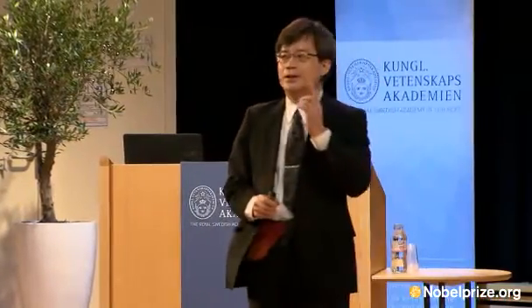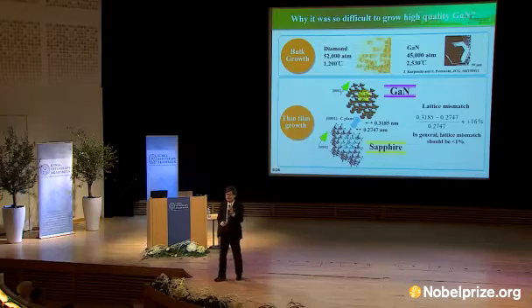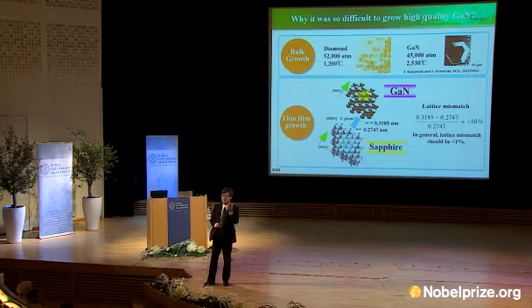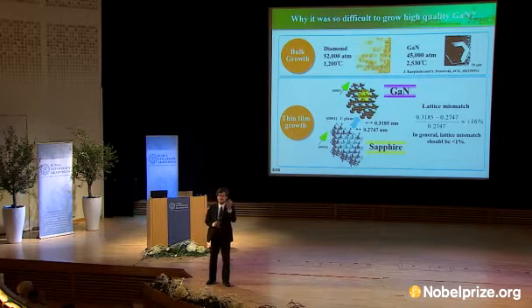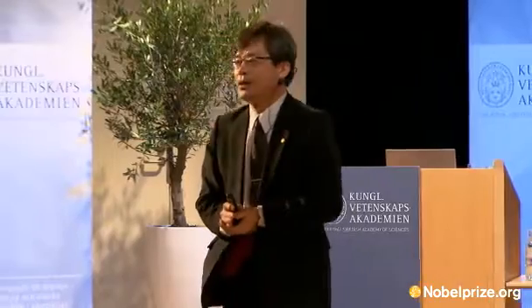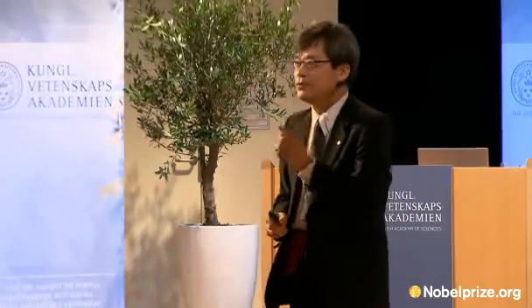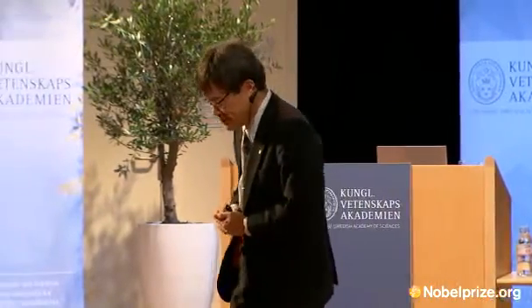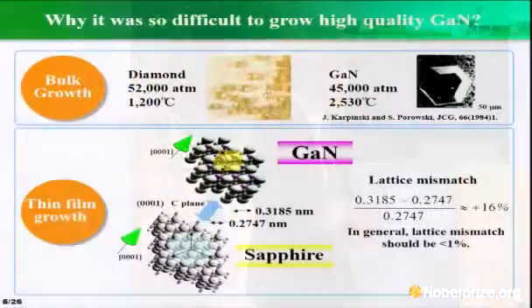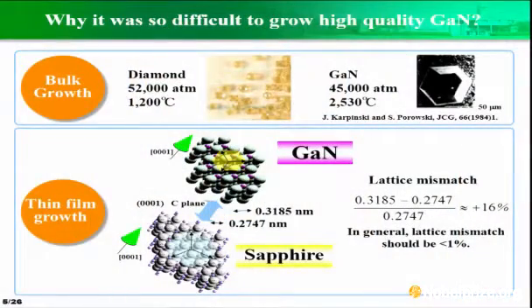But ammonia, the nitrogen source, is so reactive at high temperature. So the candidates for the substrate material are very, very limited. Sapphire is one of the most promising substrates because it does not react with ammonia so heavily. But the most serious problem of sapphire was the large lattice mismatch of 16%. In general, the lattice mismatch for heteroepitaxial growth should be less than 1%. So the 16% lattice mismatch made it almost impossible to grow gallium nitride.